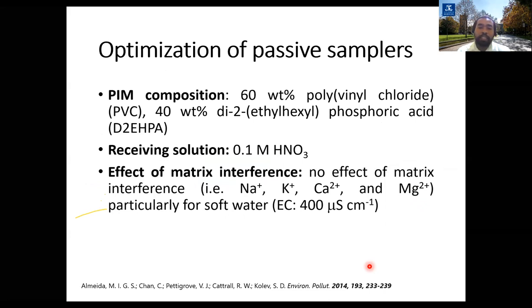There are a number of parameters that have been optimized, among which the first one is the polymer inclusion membrane composition, because this is very crucial. We have to make sure that the membrane we use is stable because it will be exposed to very extreme environmental conditions such as flow pattern, changes in temperature, and growth of biofilm, etc.